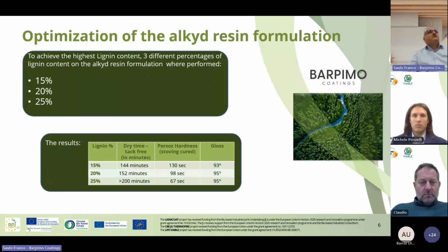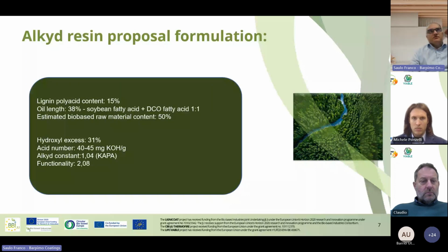And we had a modification with 25%. We saw a tack-free dry time of more than 200 minutes. For this type of resin that we are looking for, 25% was not suitable for this type of application. So then we decided to modify our formulation, focusing on 15%. And this was the proposed formulation.